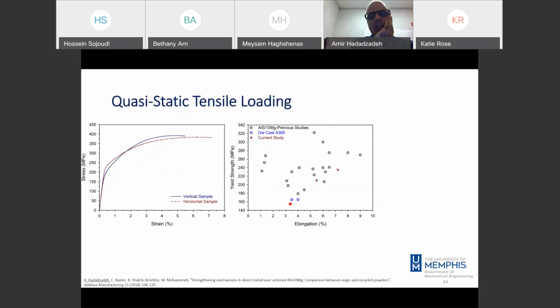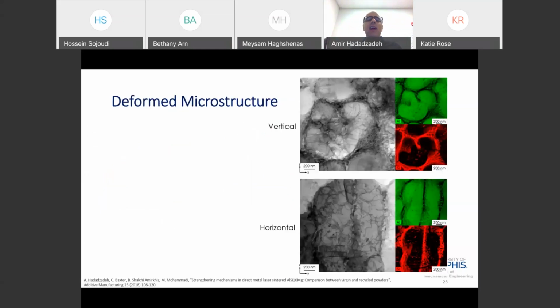So for die-cast material, the yield strength and elongation of the material are over here. But in our case, for our material, by changing the process to additive manufacturing, we were able to enhance both yield strength and elongation, as you see here. So I believe that this enhancement in both elongation and yield strength, which is unique in metallic materials, is coming from the type of the structure that we have.